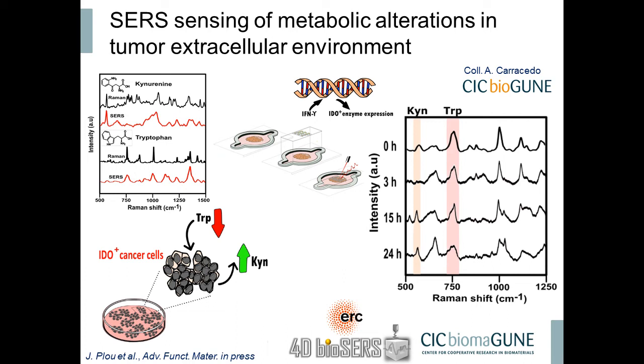And then he basically fabricated a microfluidic chip where he can grow the cancer cells in contact with extracellular matrix. One of the windows now will be the nanostructured substrate. And then by overexpressing the production of the enzyme by simply using interferon gamma, then in real time we can watch the growth of the peak of kynurenine and the drop in the peak of tryptophan.